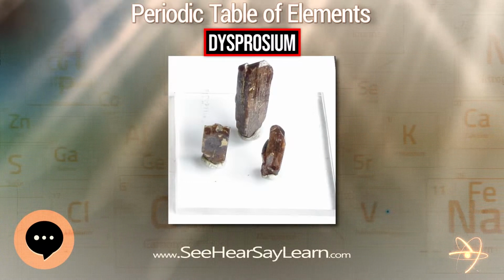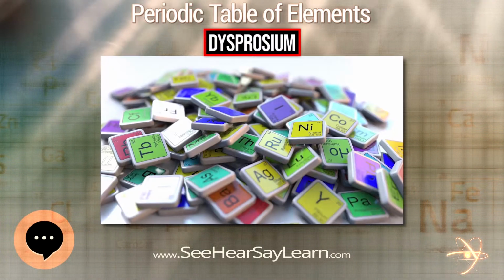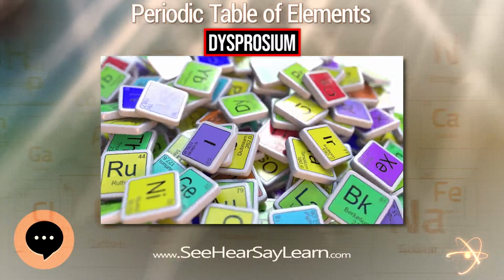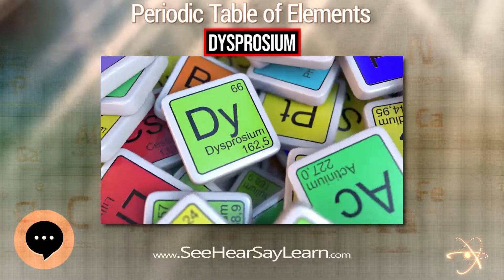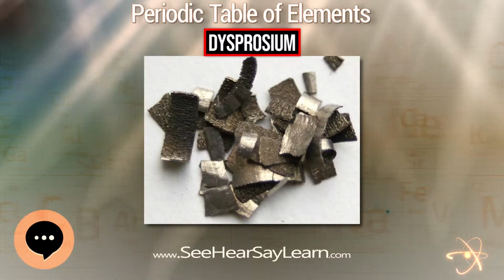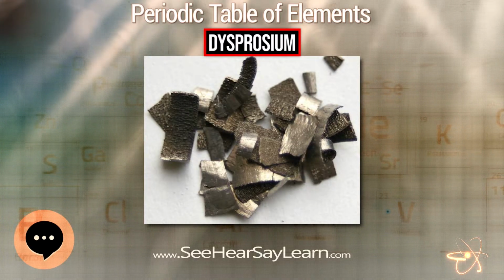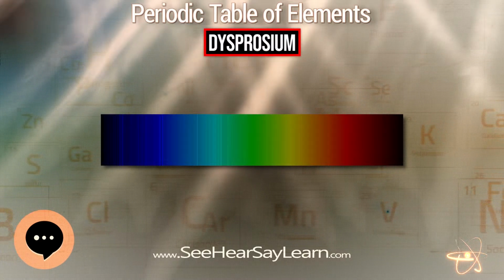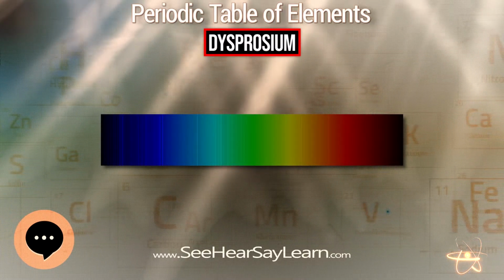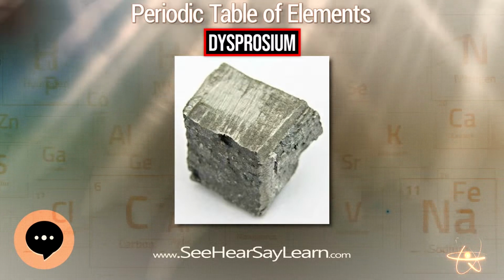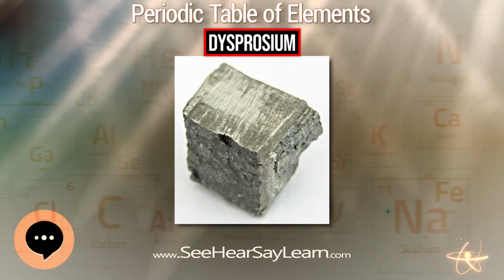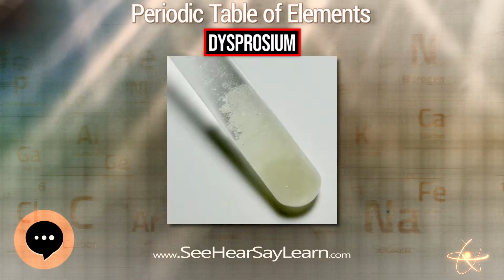Dysprosium has a simple ferromagnetic ordering at temperatures below 85 K. Above 85 K, it turns into a helical antiferromagnetic state in which all of the atomic moments in a particular basal plane layer are parallel, and oriented at a fixed angle to the moments of adjacent layers. This unusual antiferromagnetism transforms into a disordered state at 179 K.